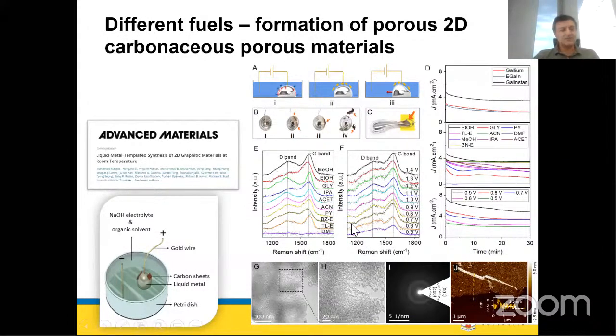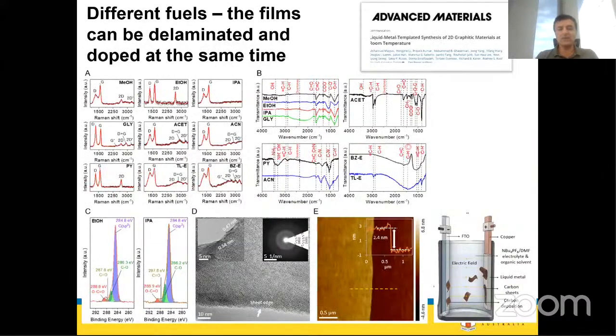We did Raman characterization, for instance. As you see, the Raman D and G bands are very broad. And when we look at TEM, zoomed in, zoomed in, zoomed in, we realize that because we have this elongation and deformation, we don't create perfect graphene materials. Instead, we are producing islands of graphitic materials, nanographene, which is very useful for many applications. For instance, making battery electrodes, which is fantastic, is holey graphene. But if you also wanted to make perfect graphene, we had a solution for that.